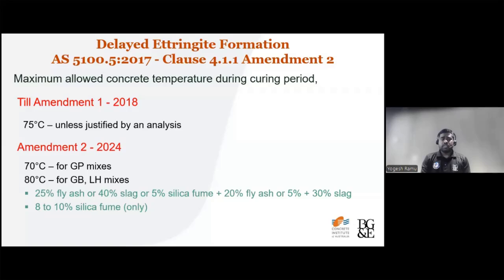Now it allows only 70 degrees Celsius maximum temperature for GP mixes, but it differentiates the GP mixes from the SCM mixes, which are currently allowed up to 80 degrees Celsius maximum temperature. This is provided the concrete has at least 5% silica fume, 25% fly ash or 40% minimum slag, or a combination of silica fume and fly ash to certain percentages. And if it is only silica fume, 8 to 10 percent in the concrete mix.